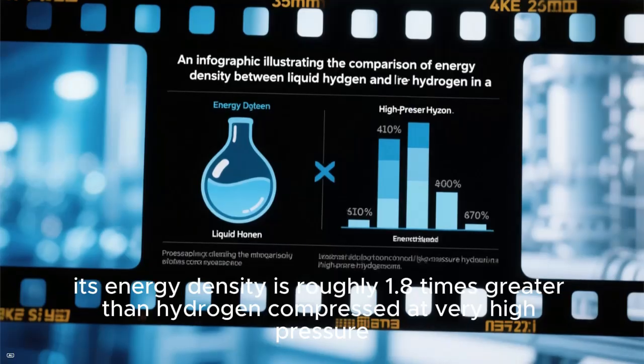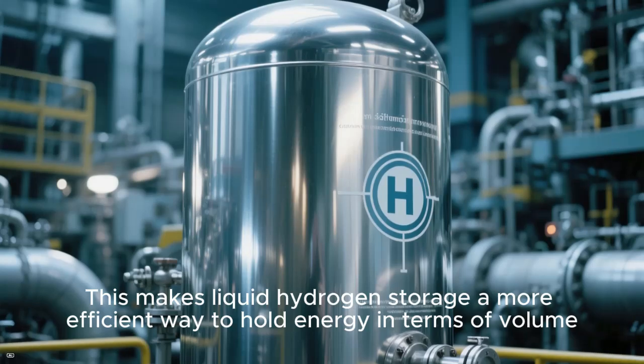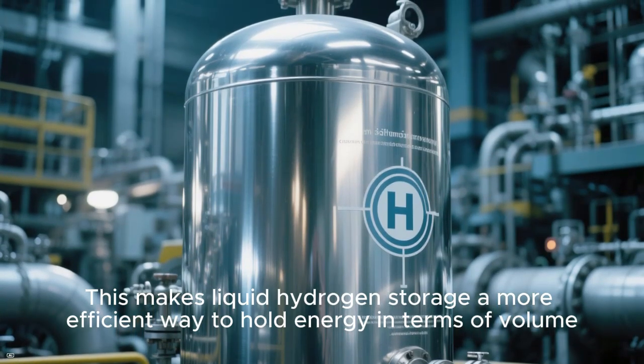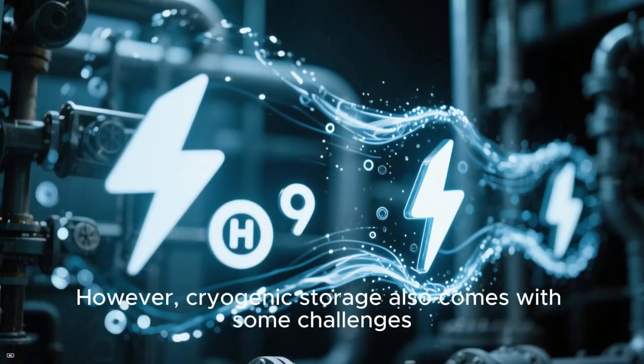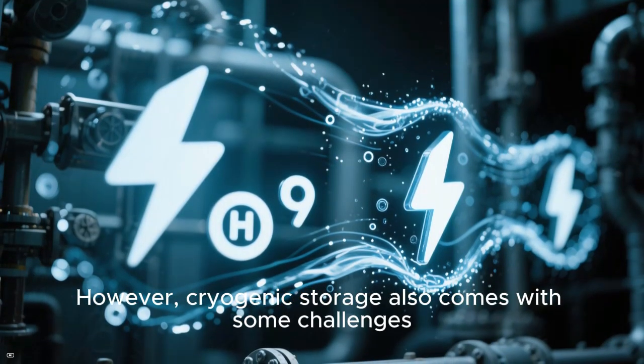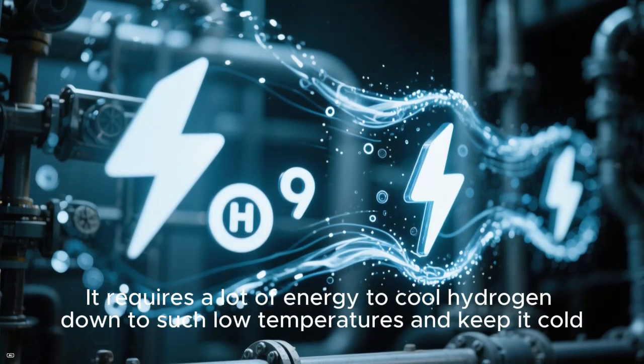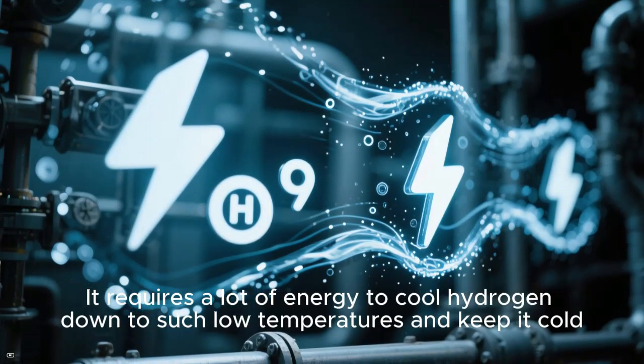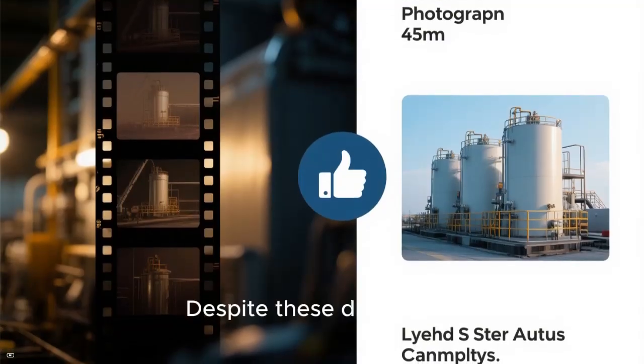At the boiling point of hydrogen, which is about 20 Kelvin, its energy density is roughly 1.8 times greater than hydrogen compressed at very high pressure, around 70 megapascals. This makes liquid hydrogen storage a more efficient way to hold energy in terms of volume. However, cryogenic storage also comes with some challenges. It requires a lot of energy to cool hydrogen down to such low temperatures and keep it cold. This high energy need can increase the overall cost and complexity of the storage system. Despite these drawbacks, liquid hydrogen storage remains an important option for storing large amounts of hydrogen, especially when space is